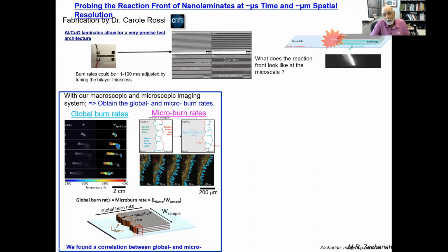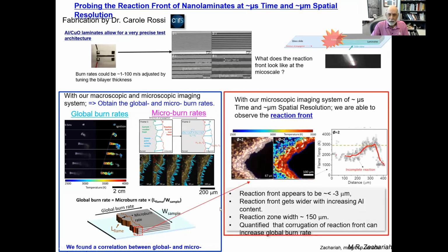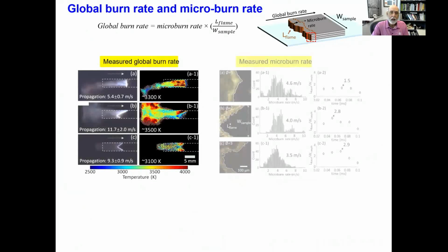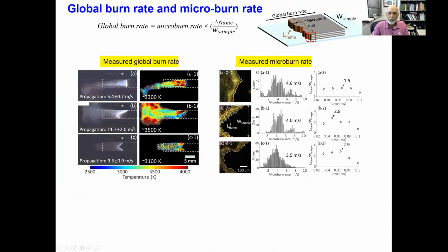Because if it is, it means you should do more of that. You should figure out ways of corrugating the flame front in order to enhance the burn rate and the energy delivery rate for the same chemistry. And so the microscopic view is shown here. These are two different times. This is what a temperature profile looks like as a function of distance in these microscopic systems. And again, we can get the corrugation of the flame front and get the velocity distribution PDF. So this is the velocity distribution, and this is the flame front corrugation.